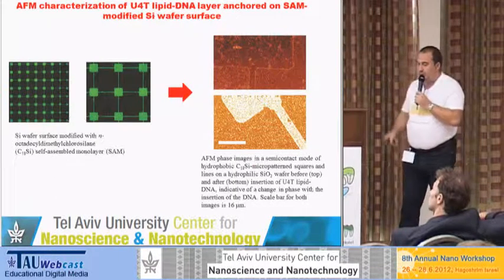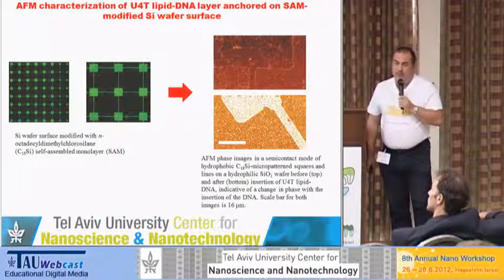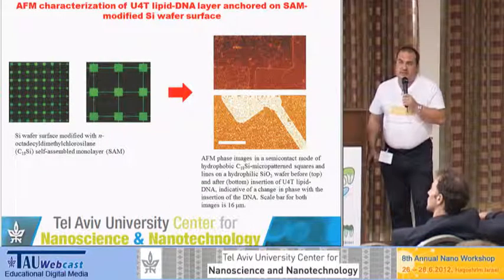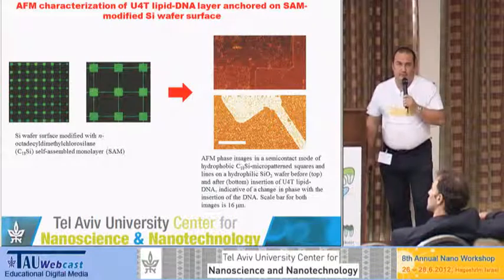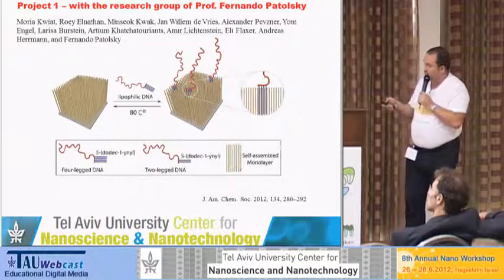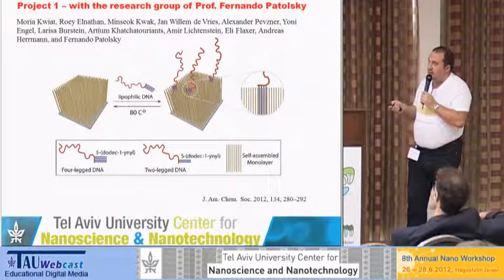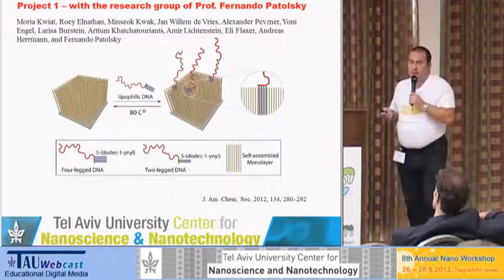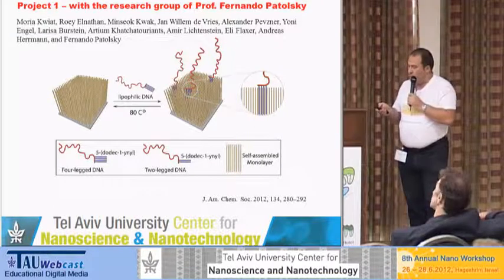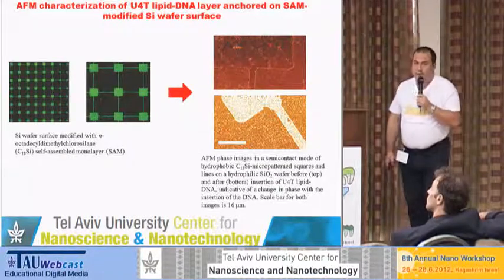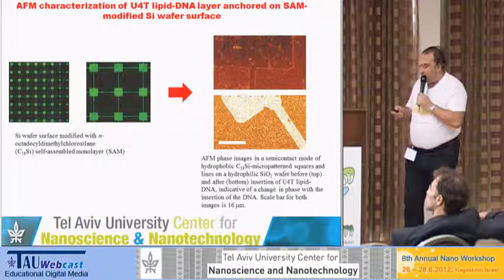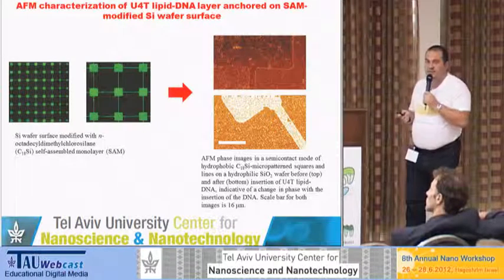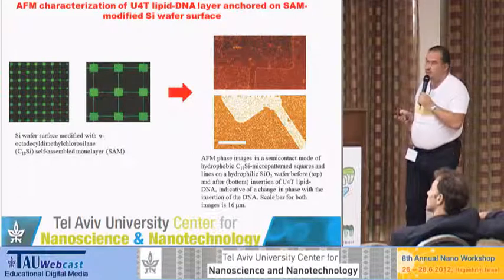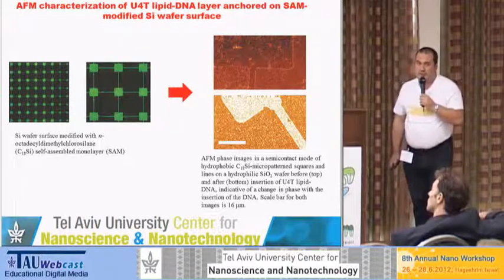And also, it appears that it can be characterized with AFM. At a first glance, there is not too much to do here with the AFM because these monolayers, they're quite thin, and attaching these molecules is not expected to change their surface roughness, for example, too much. So the height channel of the AFM is not going to give too much information. But in tapping mode AFM, as you know, there is also phase option, and the phase is very sensitive to the interaction forces between tip and the sample.